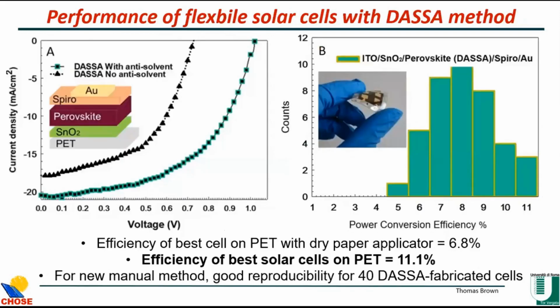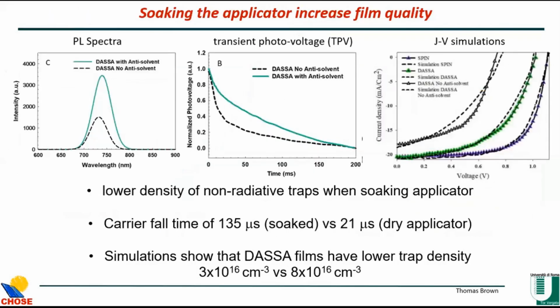And these were the best cells, the JV curves of the best cells using a dry applicator and one in anti-solvent. You can see the efficiency goes from 6.8% on PET to 11.1%. So almost doubling by just soaking. And this is a manual technique. And this is the histogram showing the reproducibility. So 11% here, 2/3 of the samples, which were 40, were 8% or above. So surprisingly good reproducibility for just a manual process.